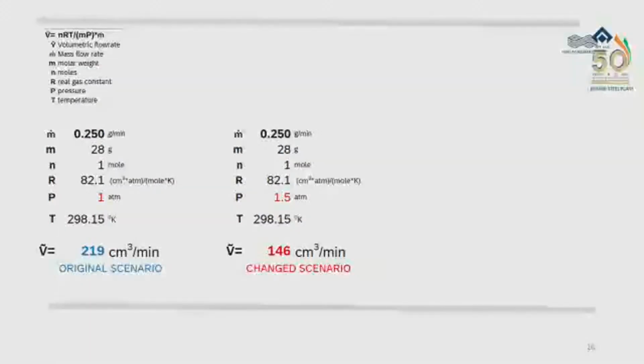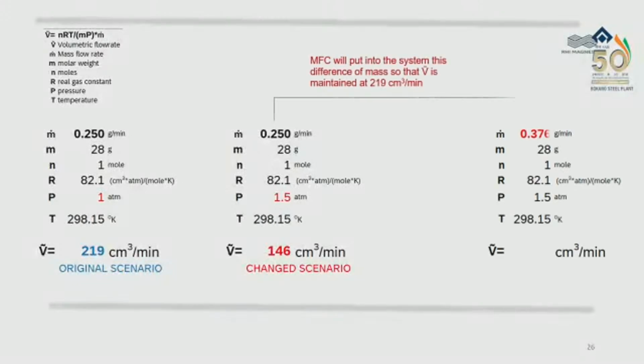So basically, this is how a mass flow rate works. See, this is the original scenario. The volumetric flow rate is coming to 219 cubic centimeter per minute. And because of the change in pressure to 1.5, I have a volumetric flow rate of 146. So the scenario has changed for me, which is bad for the plug. So what the MFC will do is work out again from 0.250 grams per minute to 0.376 grams per minute, thereby restoring the 219 cubic centimeter again, the initial state.